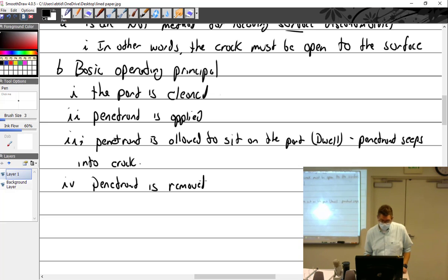That really depends on the process. If you're using visible dye that's not water washable, that's solvent based, and there are also fluorescent solvent-based penetrants. If you're using solvent based, you use a solvent remover. First wipe it all down with a dry, lint-free cloth until it's as clean as you can get it. Then put a little cleaner on another cloth and keep working until it is completely clean.